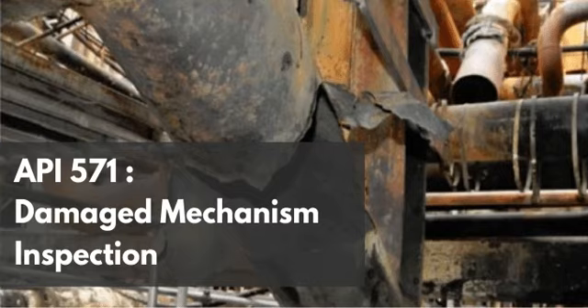Okay, so you have the water, then you introduce the carbonate ions and the H2S into that water phase. And the presence of H2S is super interesting here because I think when most field engineers hear H2S and cracking, their minds immediately jump to wet H2S damage. Oh, yeah, sulfide stress cracking or hydrogen-induced cracking. Exactly. But ACSCC is fundamentally different, isn't it? Yeah. We aren't dealing with hydrogen atoms diffusing into the steel lattice and causing embrittlement. That's a totally different physical process. Right, because this is an anodic dissolution mechanism. Yes. The H2S is playing a completely different role here. It's acting as a catalyst for the breakdown of the steel's passive armor.